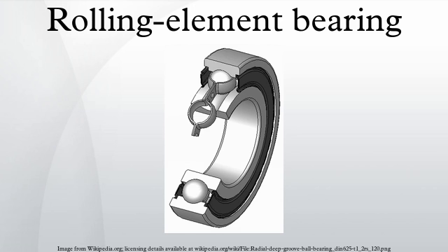A harder material may be more durable against abrasion but more likely to suffer fatigue fracture, so the material varies with the application, and while steel is most common for rolling element bearings, plastics, glass, and ceramics are all in common use. A small defect in the material is often responsible for bearing failure. One of the biggest improvements in the life of common bearings during the second half of the 20th century was the use of more homogeneous materials, rather than better materials or lubricants.